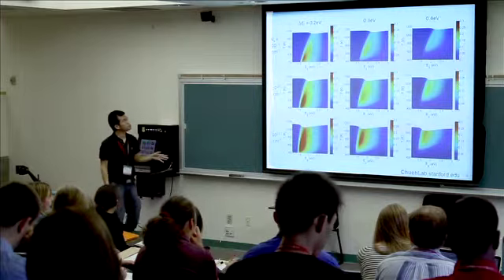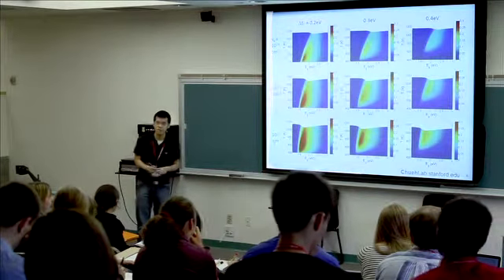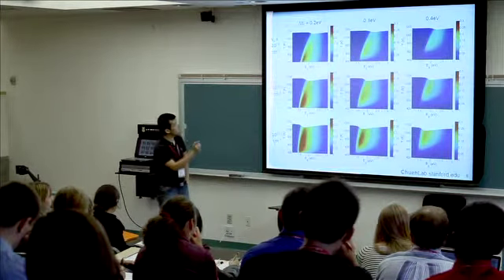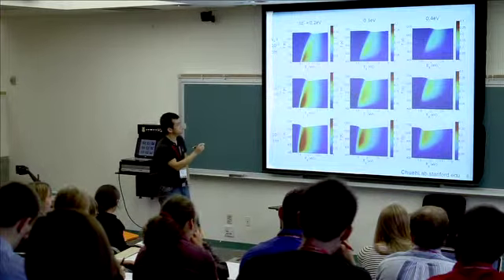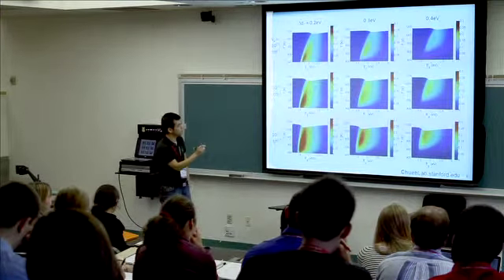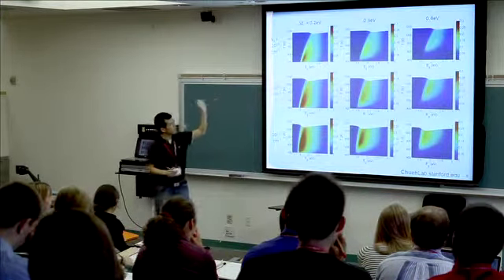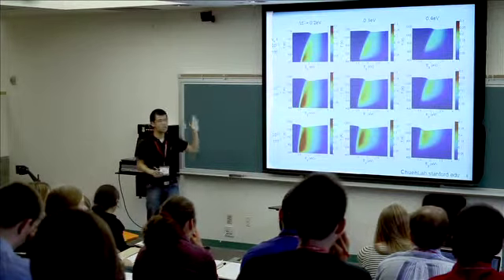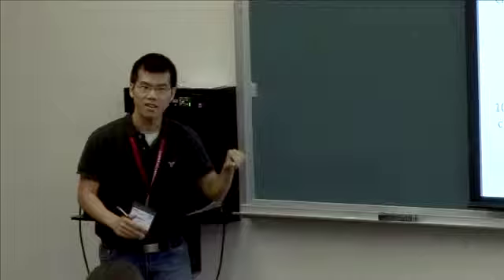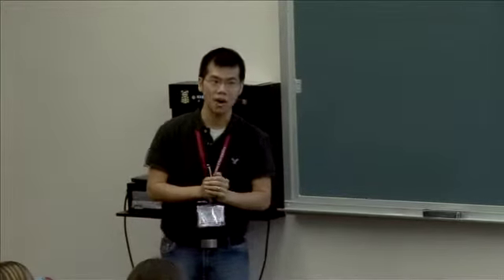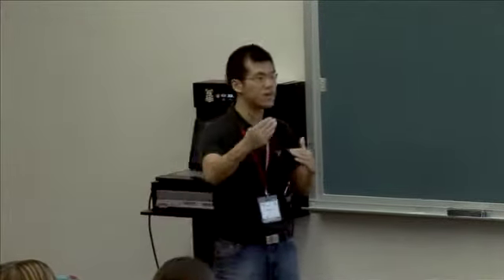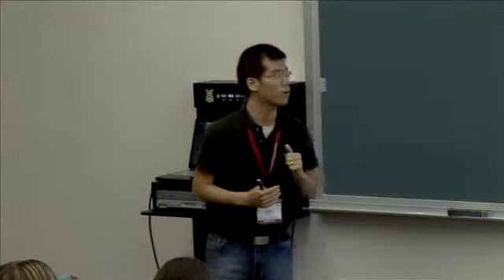These are some simulations we have run on the possible efficiency of our cell. In this contour plot here, the color represents efficiency, so red is about 30% efficiency and blue is 0. Going from left to right, we are changing what's called the band offset. This is the difference in the conduction band or the valence band offset between the two materials we were shown earlier, between the absorber and that mixed conducting oxide shell. So this is how much energetic barrier there exists.